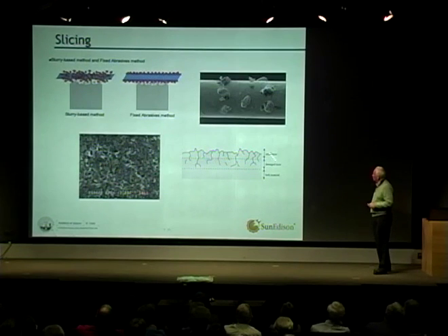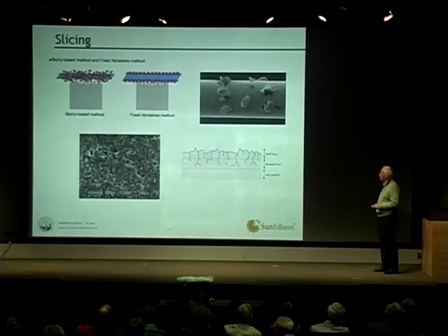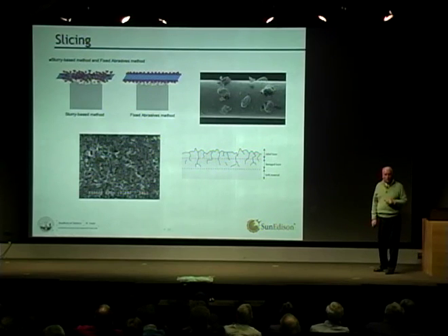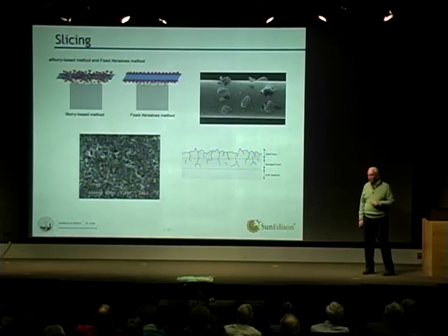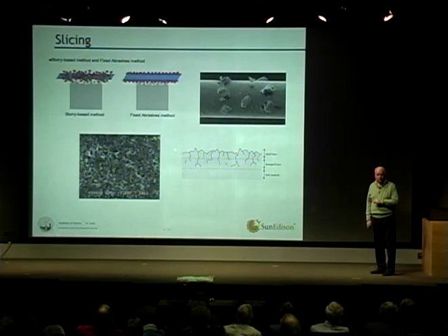So this is often broken. Here's the bulk material that we want to get to, and you've got a damage layer here. This is often called subsurface damage, just under the surface. We call this a relief layer because there's some relief here as it goes up and down. It's not perfectly flat. So the rest of the operation in manufacturing a silicon wafer is fixing the problems that the saw just created. Okay, that's not to belittle the saw too much.